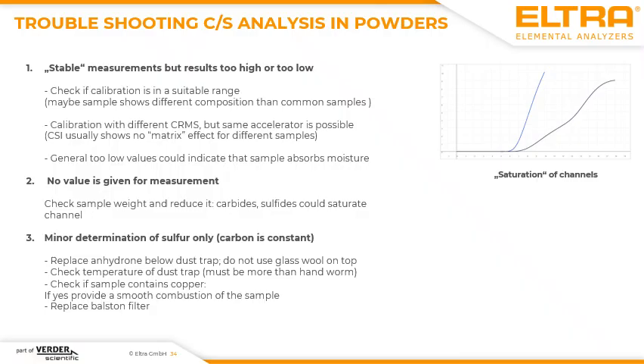When you perform a measurement but you don't get any results, then please check the measuring curves because it could mean that you have a saturation of the channels, especially for samples which have very high concentrations of carbon and sulfur. It could be possible that the IR cells are saturated and do not provide a suitable result. In such cases, only a reducing of sample weight is recommended.